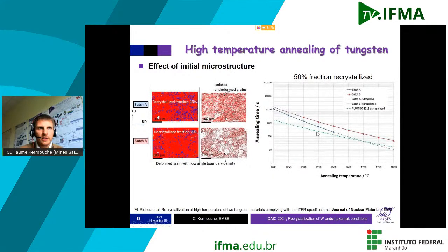Now, how to use this kind of results to design new kind of PFU? So we compared here two tungsten materials from two different suppliers. One with a recrystallized fraction of 13%, the second one with a recrystallized fraction of 8%. The difference is not significant up to us, but the main difference is in the microstructure.